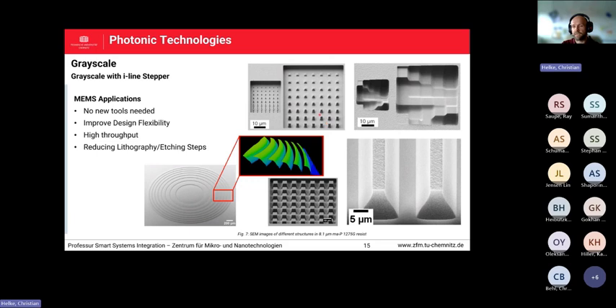It's positive tone resist here in this case, or here small staircase structures in certain transmission percentages, or side walls which can be tuned, for example, or here again some frustum structures, or even Fresnel lenses, ready to produce. So with i-line, you can use the tools which are already standing in all of the fabs worldwide, because most of the litho steps are i-line lithography steps. You have an improved design flexibility by this, going to 2D, 2.5D, and 3D. Again, it's a high throughput process, and you reduce the lithography steps and etching steps, for example, if you can deal with everything in one layer.